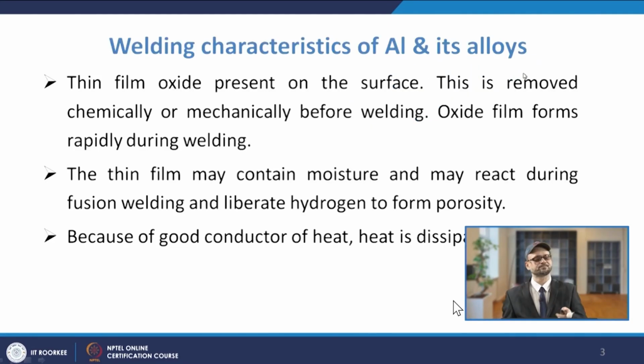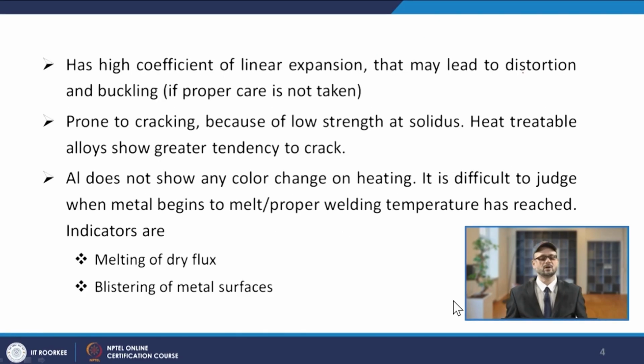Aluminum has a high coefficient of linear expansion that may lead to distortion and buckling if proper care is not taken. It is prone to cracking because of low strength at the solidus, and heat treatable alloys show a greater tendency to crack.